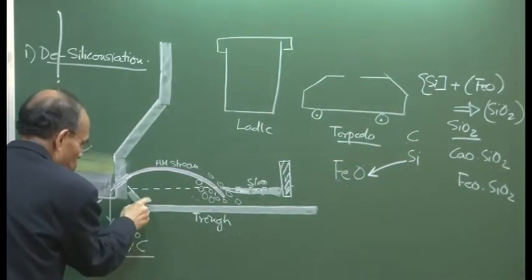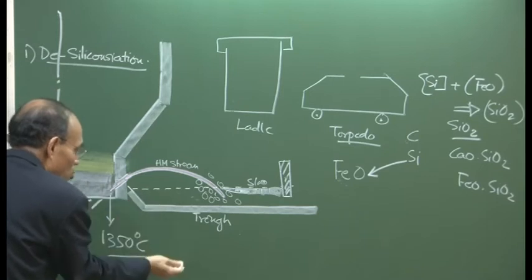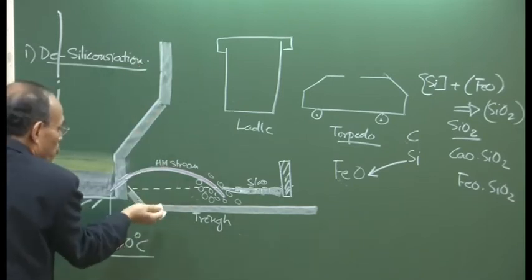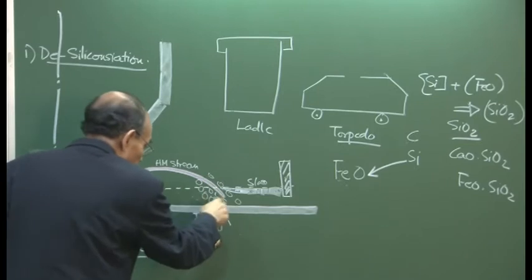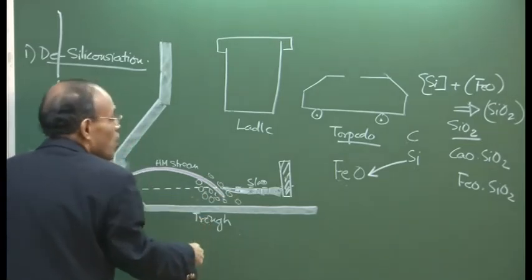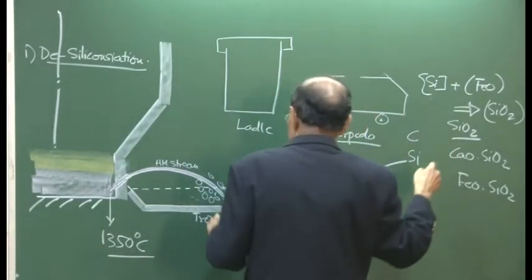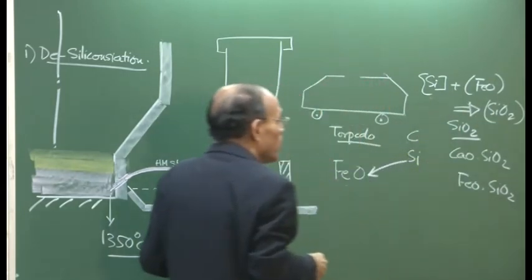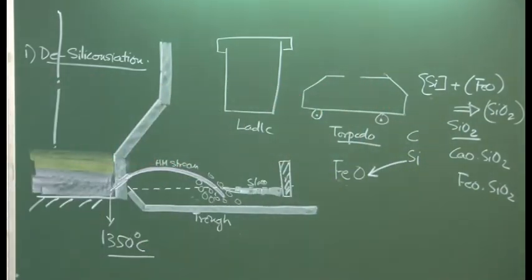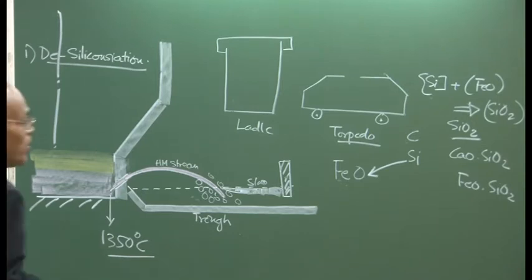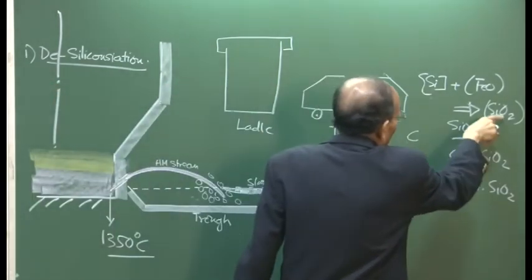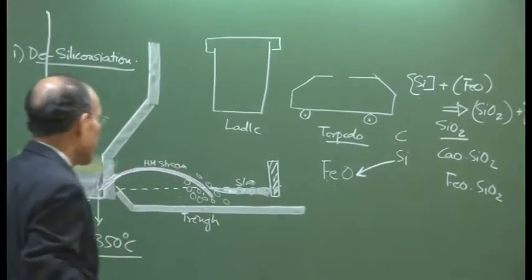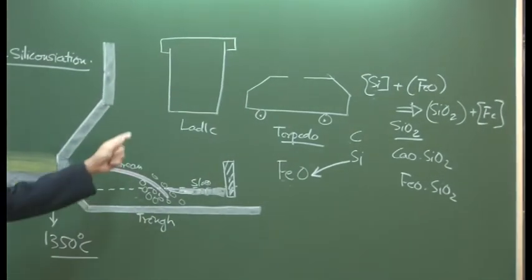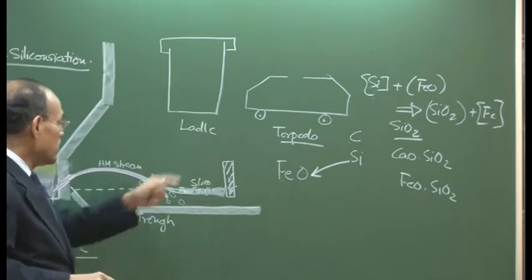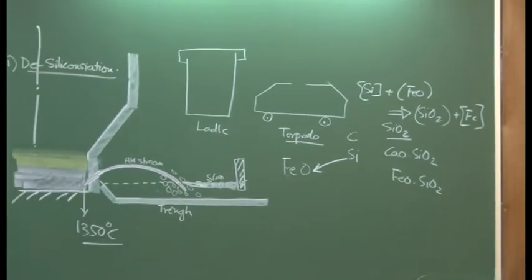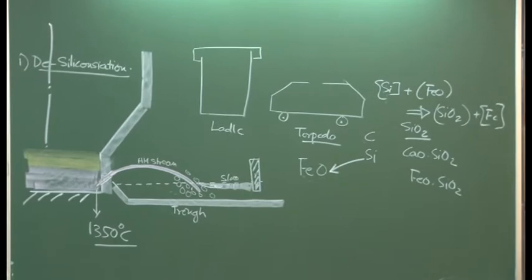In this part region, you may not see good results, a lot of silica may float up, FeO may float up to the free surface, but here good mixing condition is there. So, the slag-metal contact is a very nice site for conducting the desiliconization operation in the runner itself. We want the slag and the metal to be mixed in order to convert silicon present into silica. Alternatively, you can do the same practice here also, and you will require some kind of stirring to be applied in the system in order to expedite.